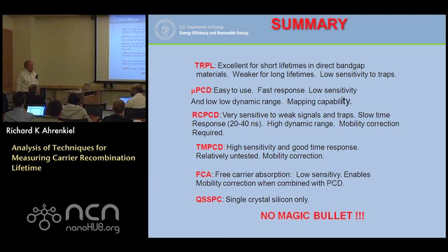Something like wafer silicon is pretty easy. It's a piece of cake. If we passivate the surface and so forth, it's pretty simple. Thin film silicon turns out to be really difficult, because as you go closer to thin film, the surfaces become dominant. I've worked on several thin film projects, and extracting a lifetime from that is really hard, because the surfaces were so dominant that I don't really know what was inside. It was completely surface dominated.